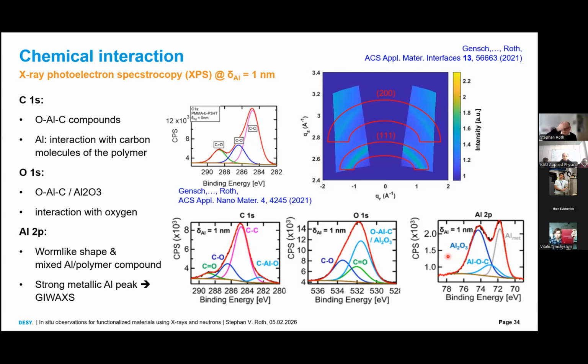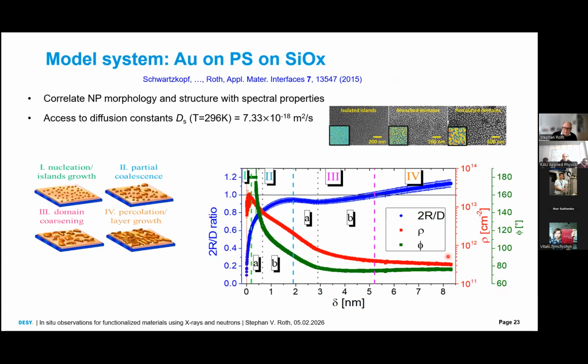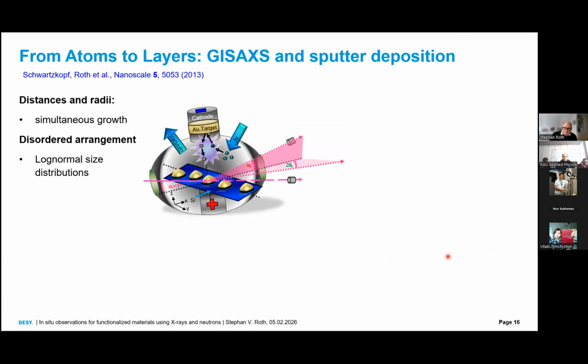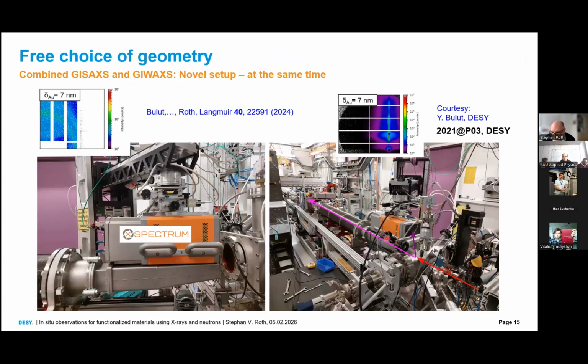I mean, we are already doing in situ measurements. If we go back to the beginning, I didn't go much into it. If you look at the image here, we even have a UV-vis setup, which is in situ. We can also measure the percolation or the electrical conductivity in situ, not 4-point, but 2-point measurement. We cannot do FTIR in situ. We cannot do XPS in situ, but we can do GISAXS, GIWAXS of course, UV-vis, and electrical measurements in situ. And with other sputter chambers, we can also deposit two metals at the same time or oxidic materials, whatever we need.